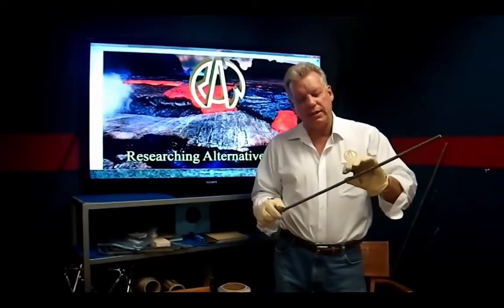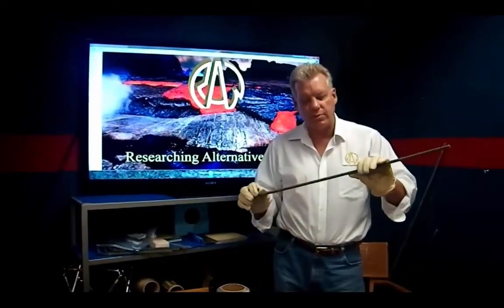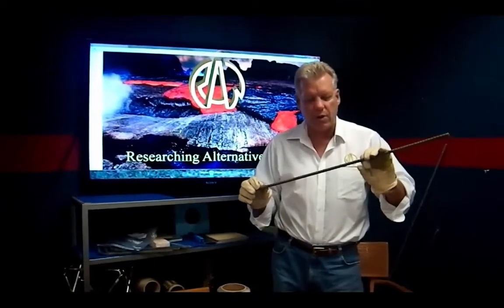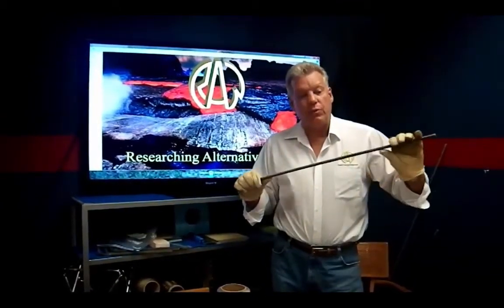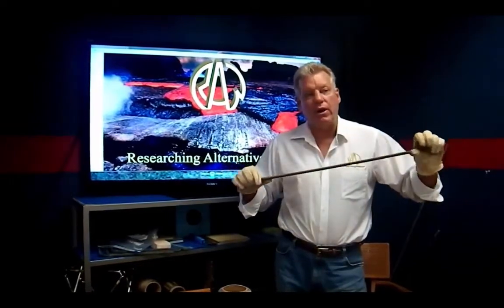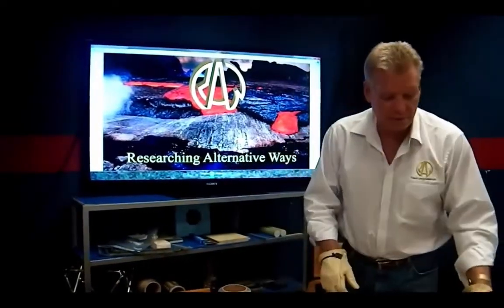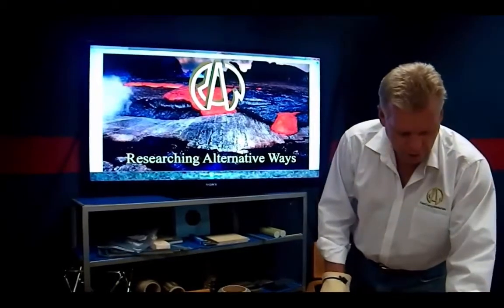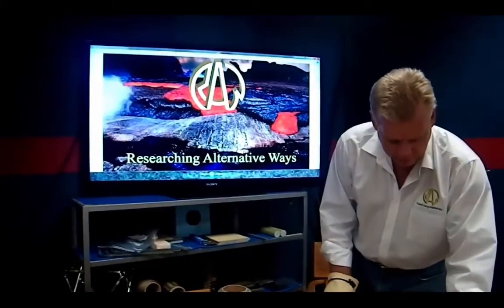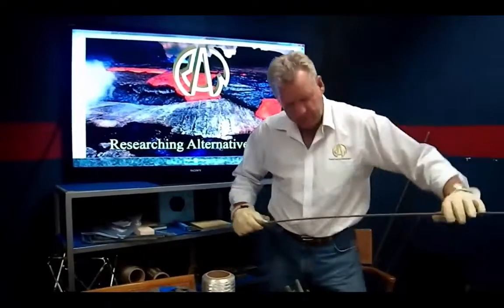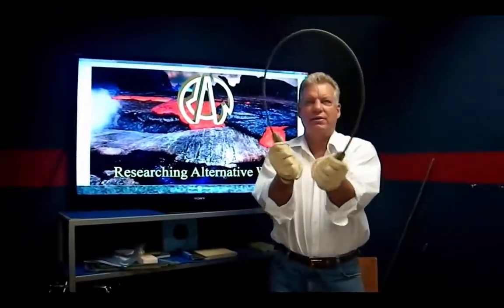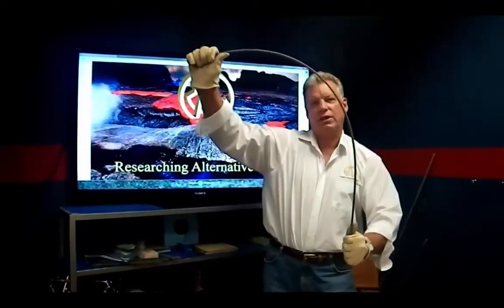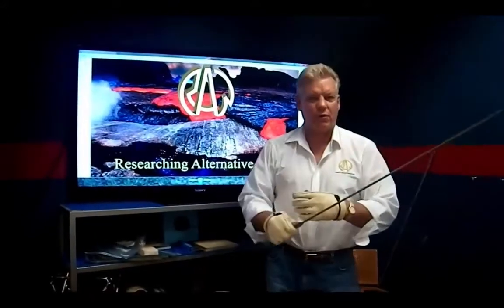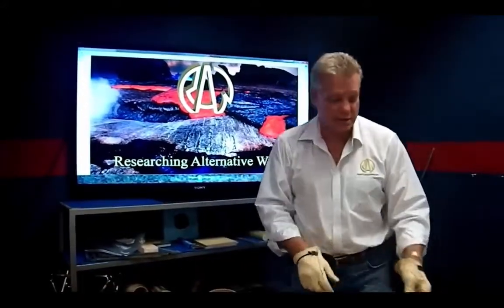With the epoxy and urethanes that we use, depending on which version of rock rebar it is, we do get a stiffness of about 110. So we're quite a little bit better than fiberglass. I'll do some smaller materials. This is 6 millimeter, and at this level, not only will it not break, it'll bend. The swimming pool guys love this because you can see that it would make a really nice corner for a pool. You don't have to play games with bent steel.